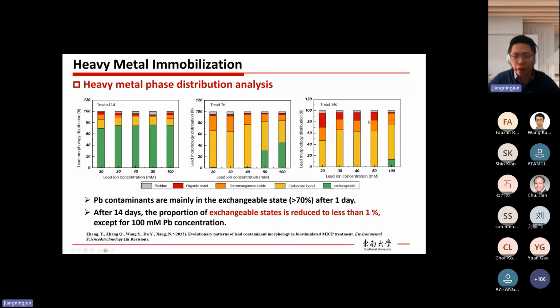Then after 14 days, for 20, 30, 40, and 50 millimole lead concentration cases, we could say that the exchangeable state is reduced to less than 1%, and mostly they are in carbonate bond. Even for the 100 millimole case, the exchangeable state only has less than 20%. So this could further demonstrate that MICP could help to immobilize heavy metal, could change it from unstable state to more stable state.